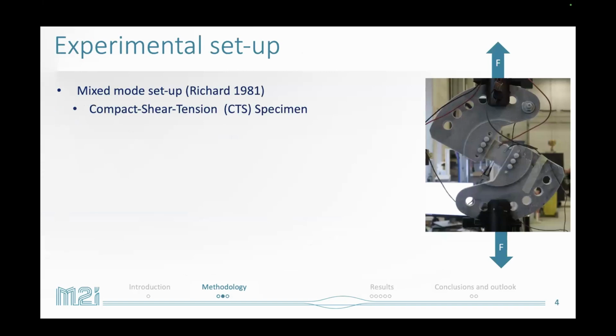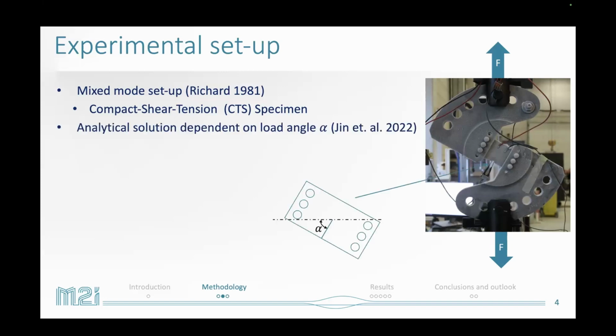So this setup, these compact tension shear specimens, were developed by Richard in 1981, and you see here a picture of the setup. It consists of the specimen in the middle with 2 grips, loaded in a hydraulic machine, so a vertical load applied. But because you can change the orientation using these 7 holes, you change the mode mixity between a pure mode 1 test and a shear test. So the solution depends on the load angle alpha, or that's how I call it in this slide. So we have 7 discrete angles, and then there are analytical solutions available to calculate what the stress intensity field is depending on this angle.